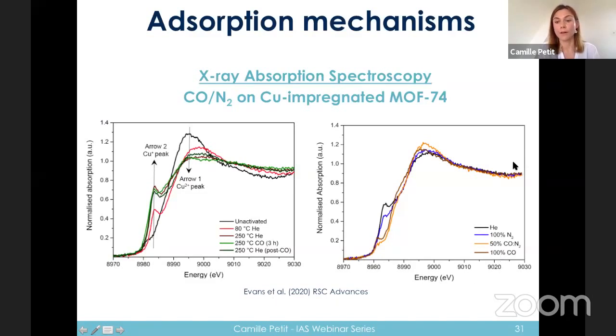And the graph here on the right shows similarly the evolution of copper 1+ and copper 2+ upon adsorption of first nitrogen and then a mixture of CO and nitrogen, then fully CO. And what you can see here is that we have a decrease in the intensity of the peak corresponding to copper 1+, which is an indication of the interactions between CO and copper 1+.